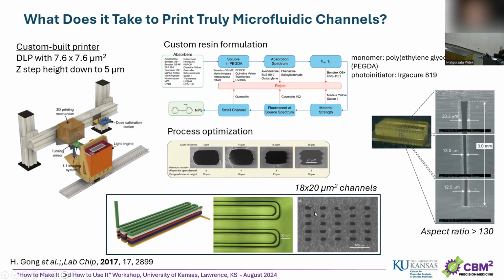So think about this. If you were trying to make a design like this by milling, you would have to make each one of those layers separately and then put them all together. Here, you can print it in one shot. They were also able to do really, really high aspect ratio structures, over 130, right? So the channel was 3 millimeters tall and somewhere 12 microns at the bottom and 23 at the top. And you can actually see all those individual layers.